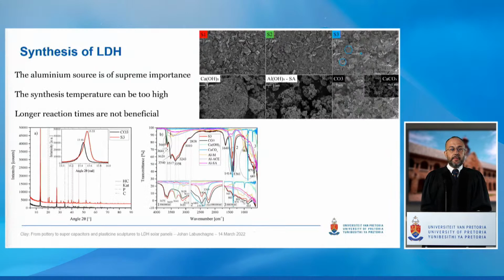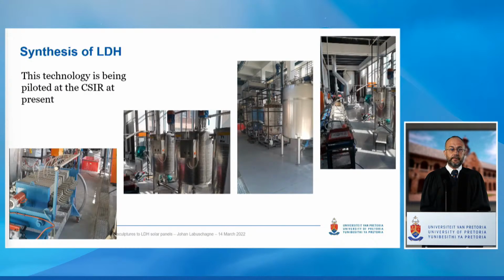We found that the aluminium source was of supreme importance. If you used the wrong aluminium source, we actually had no reaction. So choosing the right aluminium hydroxide for the synthesis was crucial. Another interesting fact from this was that increasing the temperature and the time for reaction was not beneficial like it was for the magnesium aluminium LDH. In this case, going too high in temperature or too long in reaction time actually destroyed the material.